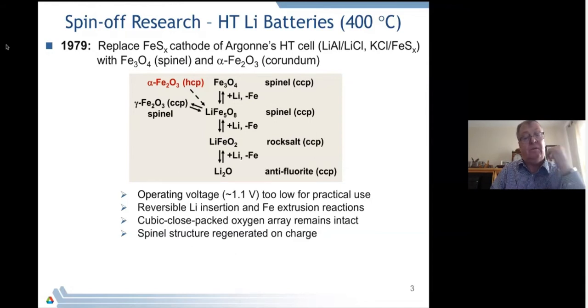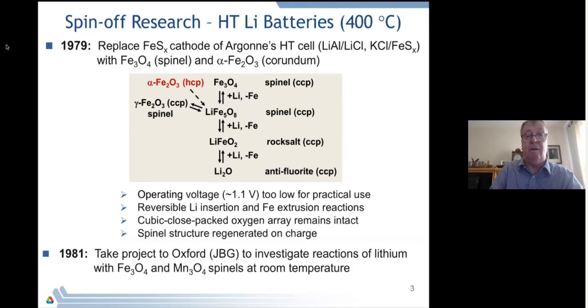But the beauty of these reversible insertion and extrusion reactions was that the cubic close-packed oxygen array remained intact during the electrochemical process. But in each case, the Spinel structure was regenerated on charge, particularly in the case of Fe3O4. If one started with alpha Fe2O3, which was hexagonally close-packed, on charge, that didn't go back to that particular crystalline form, but rather to gamma Fe2O3 Spinel. So there was something going on in the stability of Spinel framework structures and rock salt.